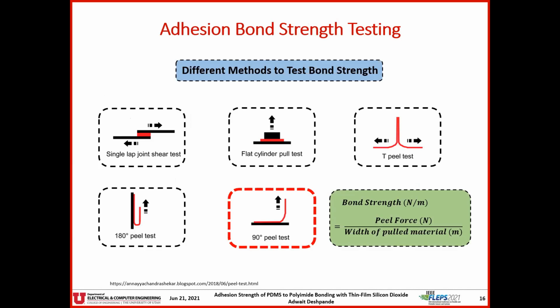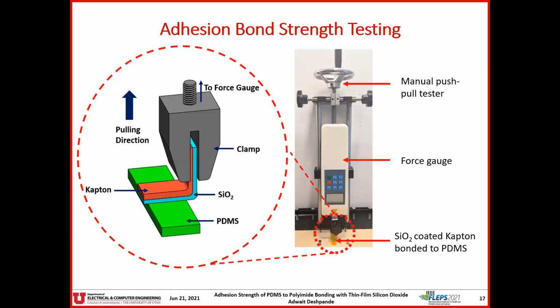Different methods to analyze the bond strength by peel testing are shown. In our experiment, we have used the 90-degree peel test. Bond strength was calculated by dividing the peak peel force with the width of the peeled Kapton film. From this pull testing setup, we can see that the PDMS block is clamped to the bottom and the overhang of the bonded SiO2 coated polyimide is pulled vertically. The force gauge was configured to measure the peak peel force.